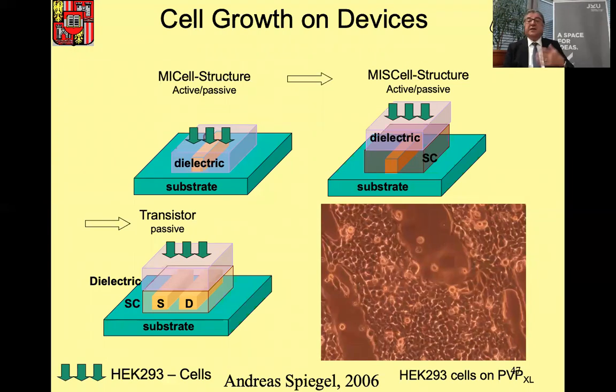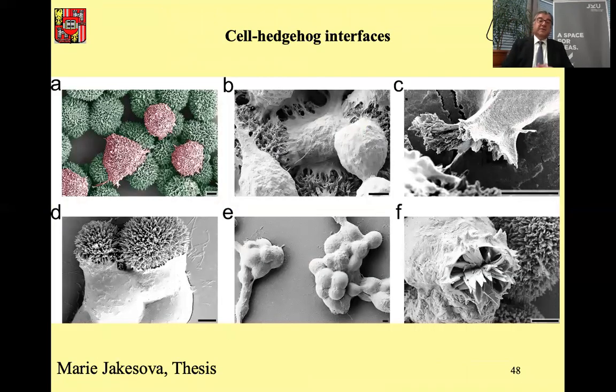Second, of course, is that our living cells and bacteria and biosystems are growing on these organic semiconductors. Is there some kind of possibility that we can indeed use these materials as substrates for cells to grow on? And now comes these famous hedgehog nanoparticles. Indeed, this was the Marie Jakesova thesis. These hedgehogs are quite interesting because living cells are attracted and bound to these hedgehog structures with great strength. It's unusual that the same material in a plain thin film has a different settling of biosystems on it than these hedgehogs. Apparently the cells love these kinds of hedgehog structures and they grow on that quite nicely.